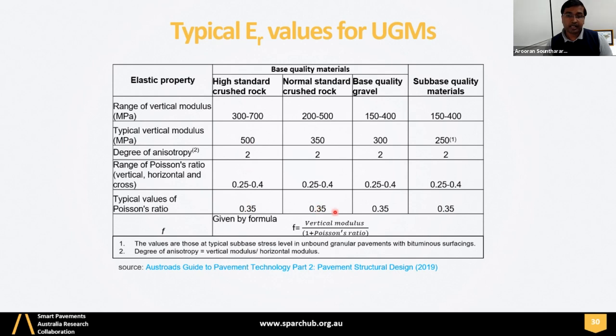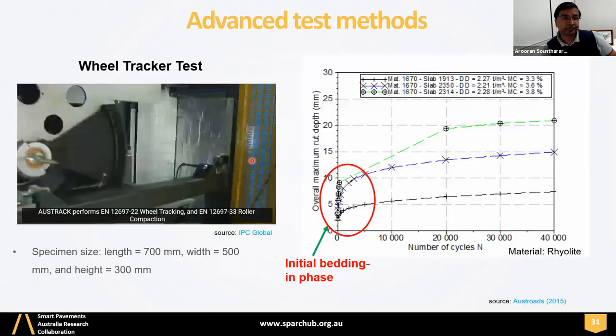And the Poisson ratio values are also marked here, 0.35, and degree of anisotropy is 2. That means your vertical modulus and horizontal modulus are not the same. Normally they use factor 2. That means the vertical modulus is equal to 2 times the horizontal modulus in the pavement structural design.